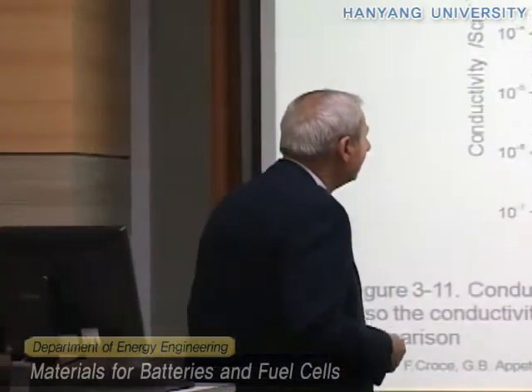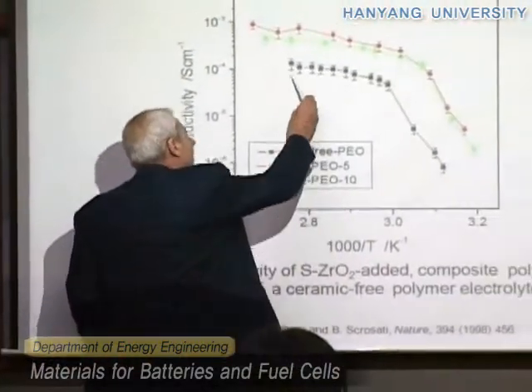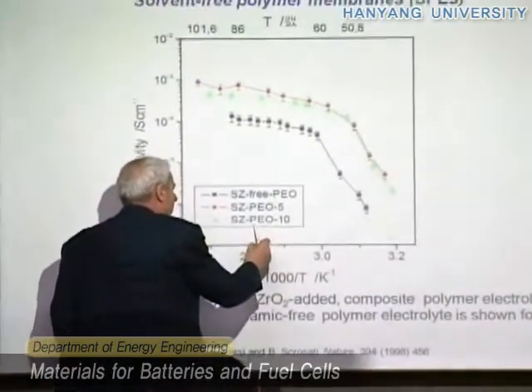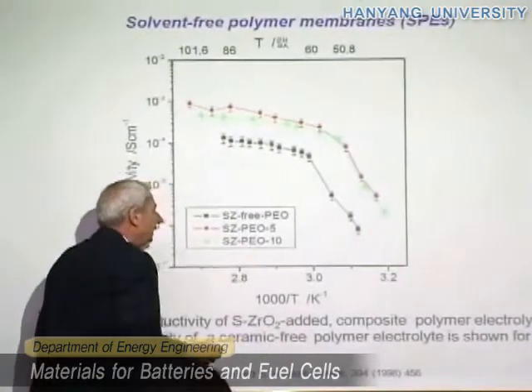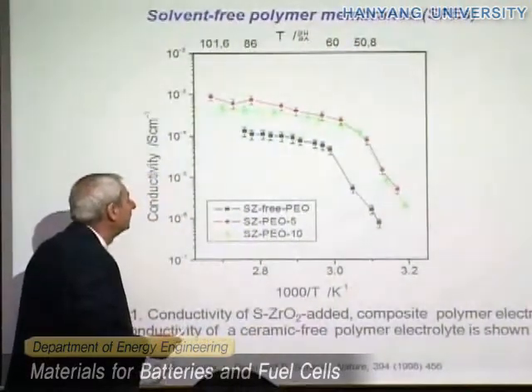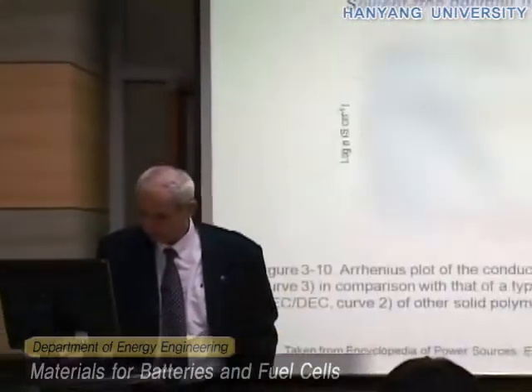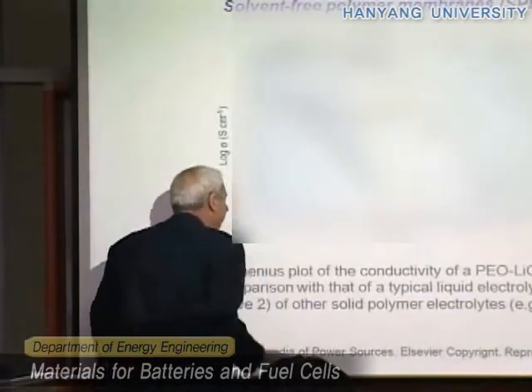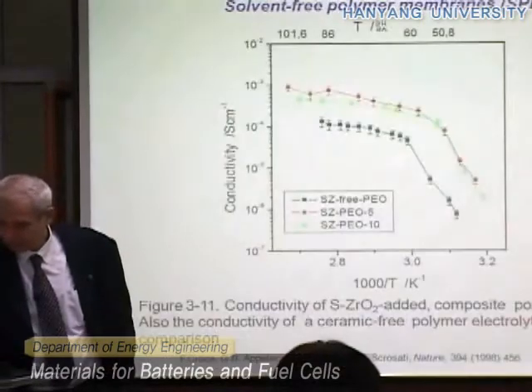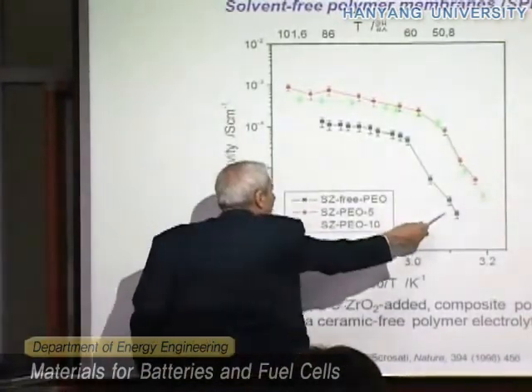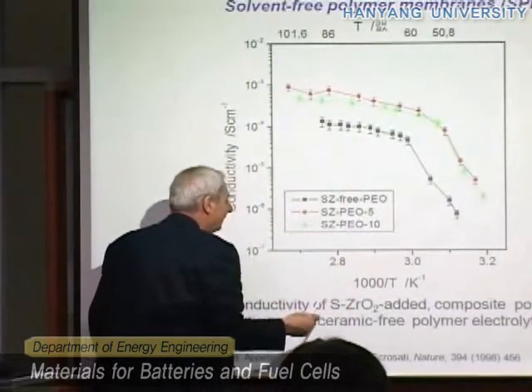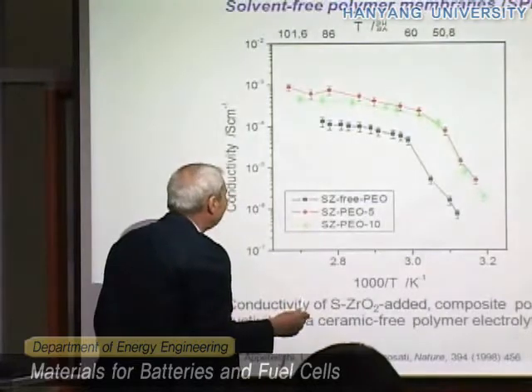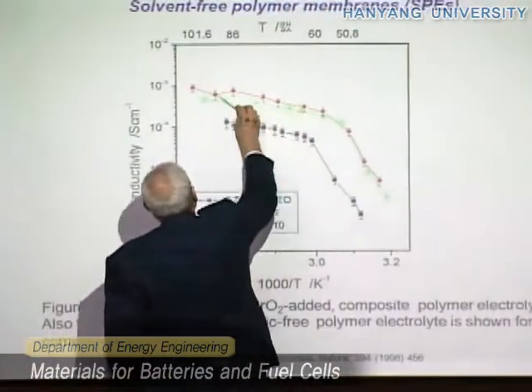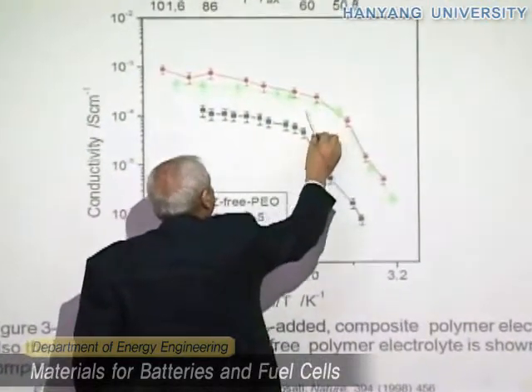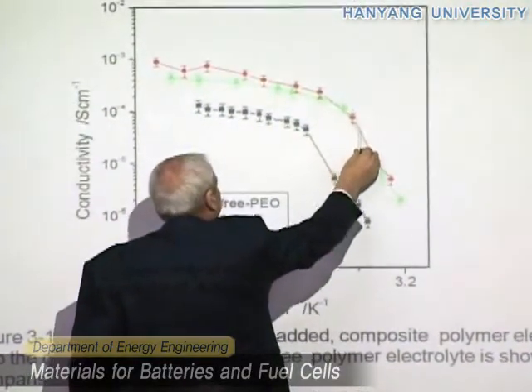Arrhenius plot that this is the conductivity of the normal PEO, this one. And this is very similar to the one that I showed you before, one you see here. This is this one, all right, about 10⁻⁴ to 10⁻⁶. And here, 10⁻⁴, 10⁻⁶. But if we add some of these ceramics, we raise the conductivity almost 1 order of magnitude. And the break also is happening at a temperature a bit lower.